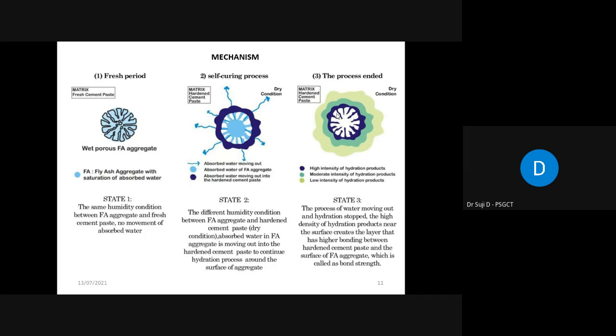So the self-curing process starts with this difference of humidity. So the difference of humidity conditions between the fly ash aggregates and hardened cement paste is initiated. So absorbed water in fly ash aggregate is released into the hardened cement paste to help the hydrated cement paste use that water, so that any unreacted cement particle found in that medium or that place will take that water and start hydrating. So the hydration process is continued even in the non-availability of external water. And the process ends when it ends.